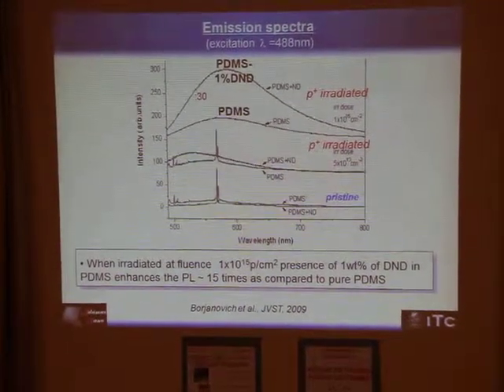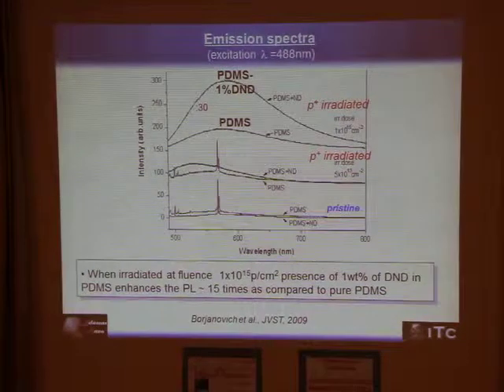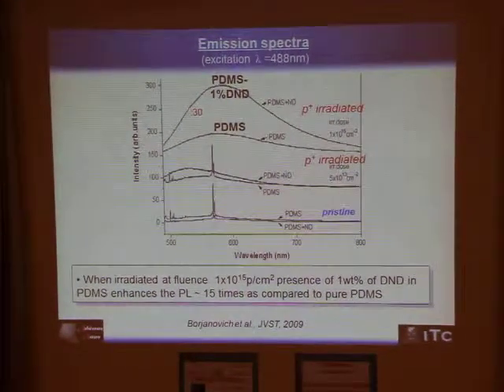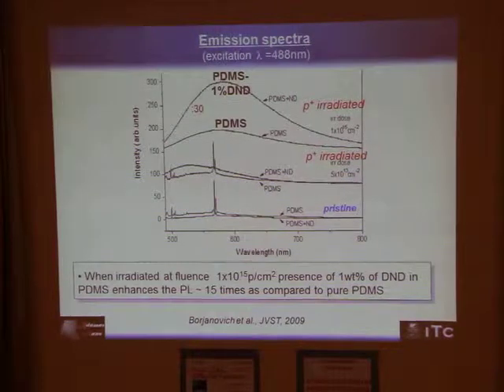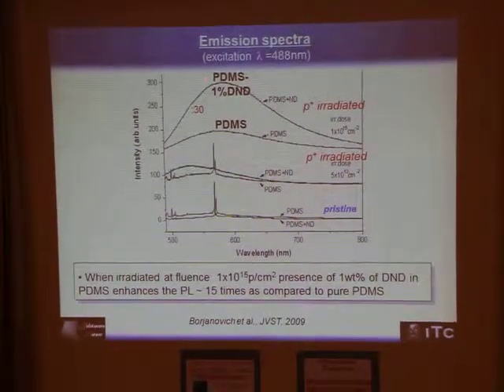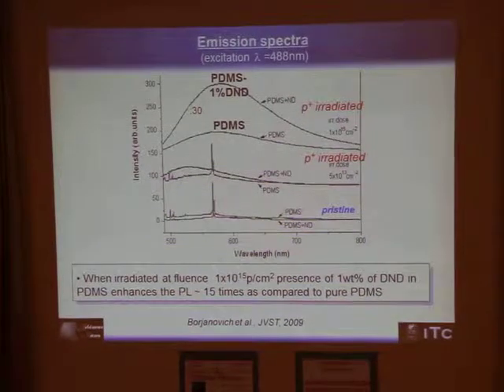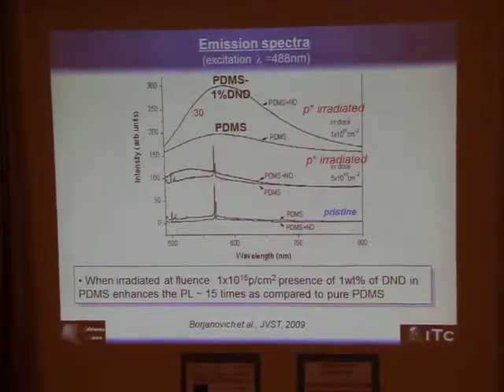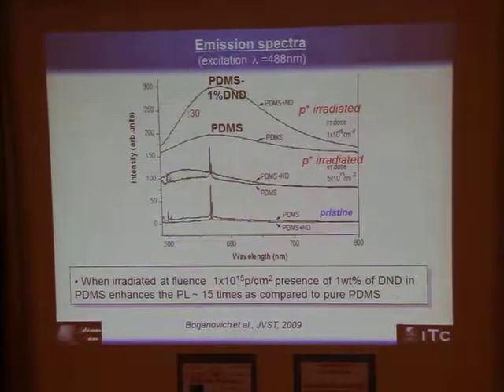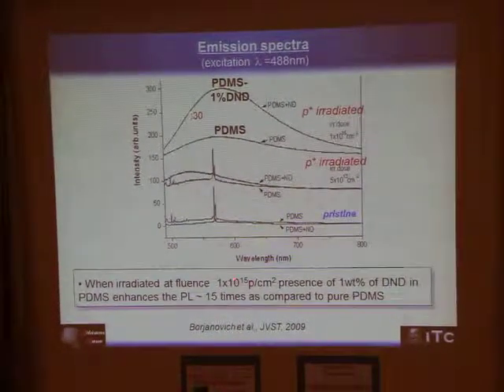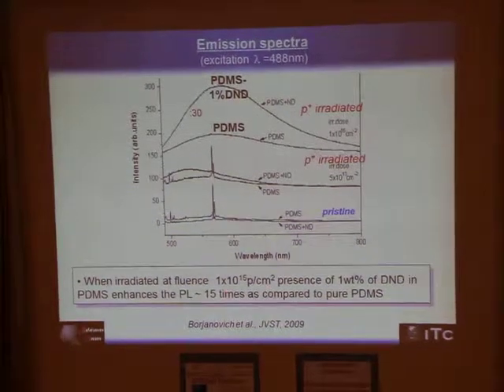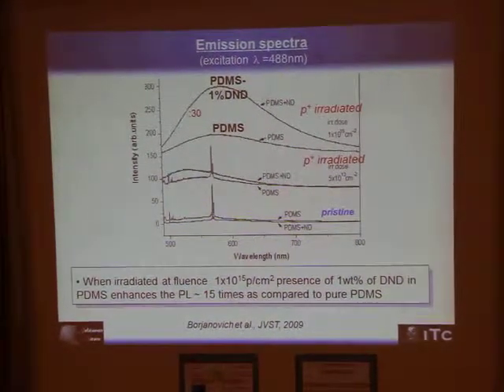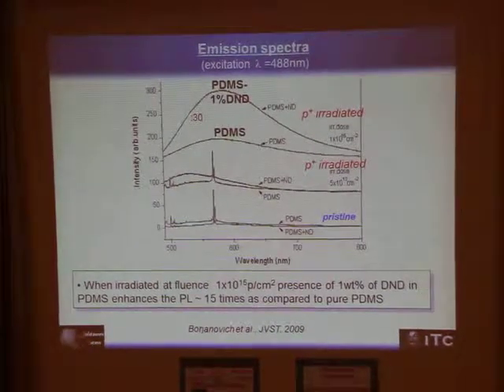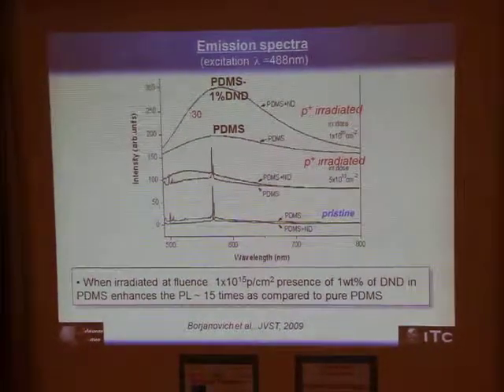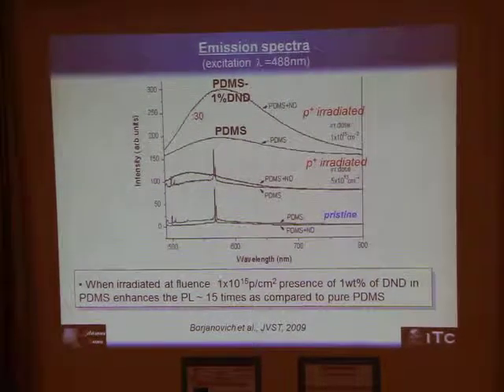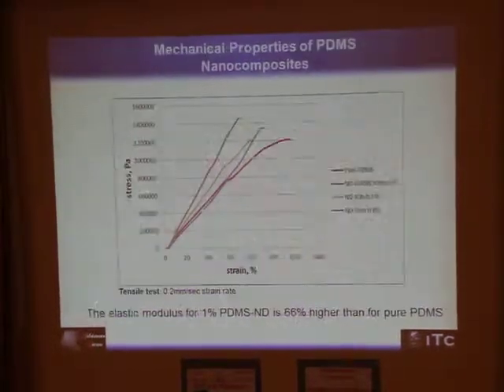And finally, this slide shows us the photoluminescent intensity for the highest dose of irradiation, and it appears that the presence of nanodiamond, when the composite is irradiated at 10 to the power 15 protons per square centimeter, is 15 times stronger than pure PDMS. So it's a very interesting phenomenon that the presence of nanodiamond greatly enhances photoluminescence of the PDMS composites.